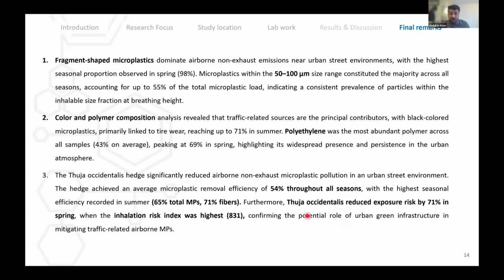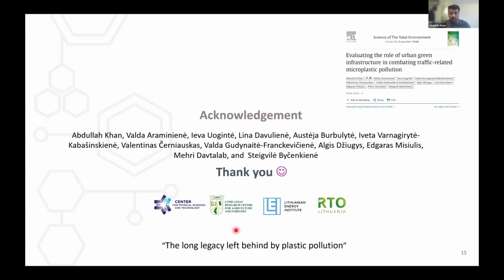The hedge achieved 54% efficiency throughout all the seasons, with the highest removal efficiency recorded in summertime for total microplastic, 65%, and 71% for fiber. Furthermore, Thuja occidentalis reduced exposure risk by 71% in springtime when the inhalation risk index was highest at 831, confirming the potential role of urban green infrastructure in mitigating traffic-related airborne microplastic pollution.